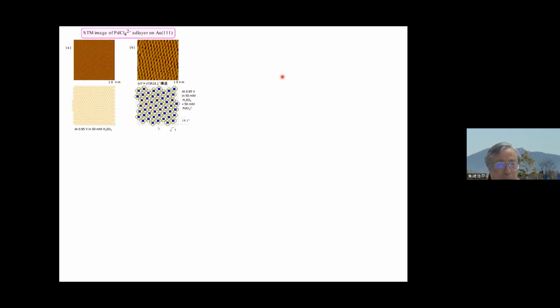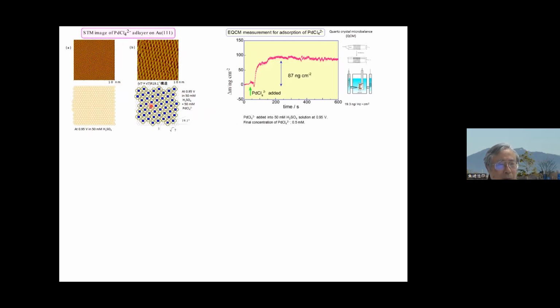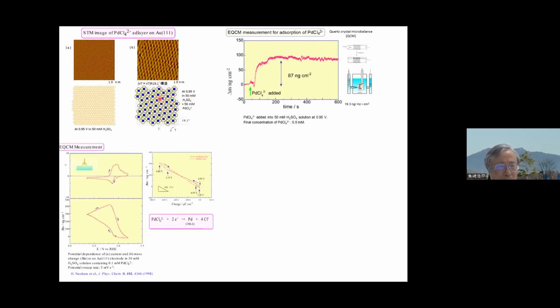of the tetrachloropalladate. Of course, this means the tetrachloropalladate adsorbed in this way, but it doesn't mean it adsorbed as a monolayer. So we used an electrochemical quartz crystal microbalance to study the weight change. The electrode is covered with gold, so when the tetrachloropalladate adsorbs on the surface, the resonance frequency goes down, and you can convert it to the weight change, which is 87 nanograms per square centimeter, which corresponds to a monolayer of this structure. So it is confirmed that a monolayer of this molecule adsorbed on the surface.